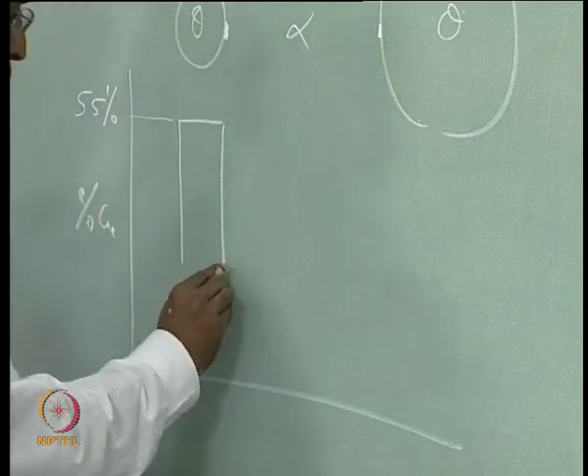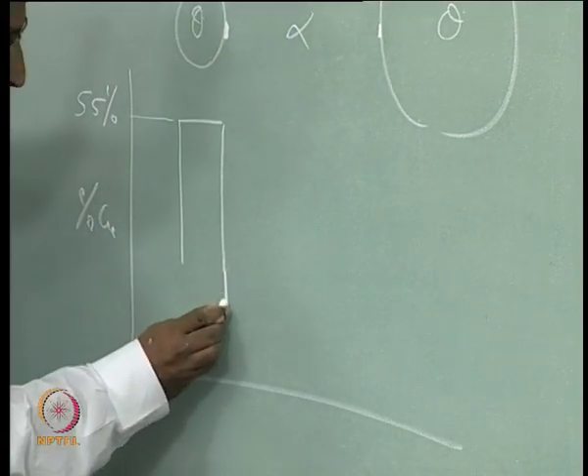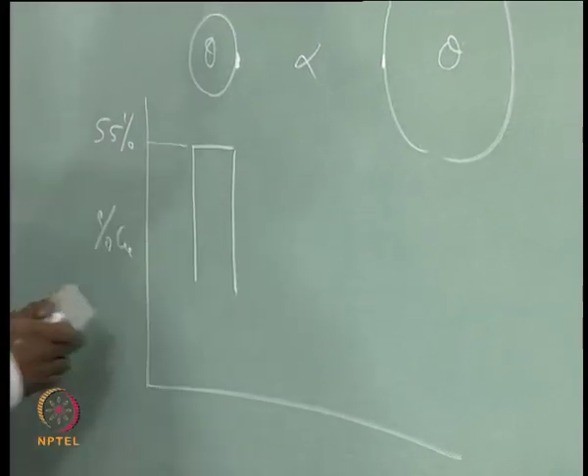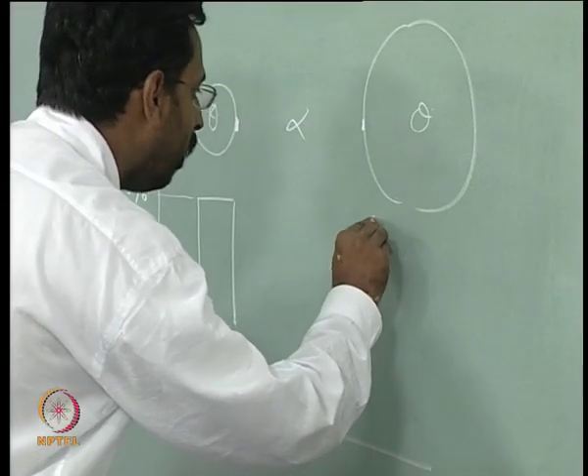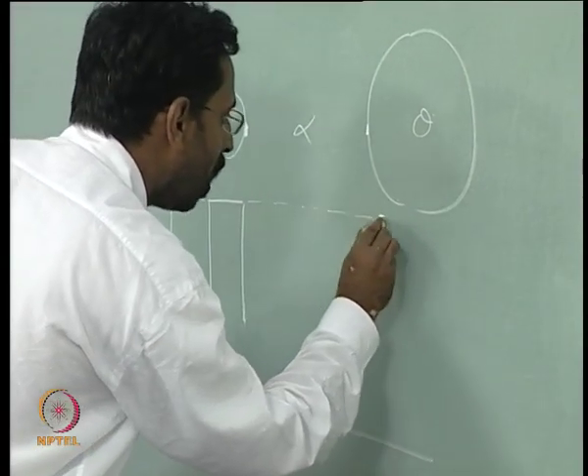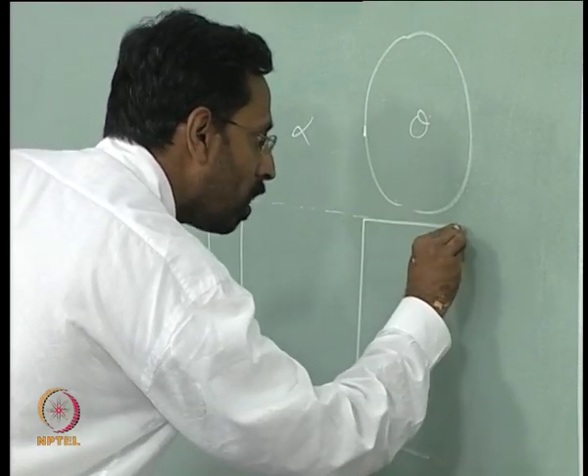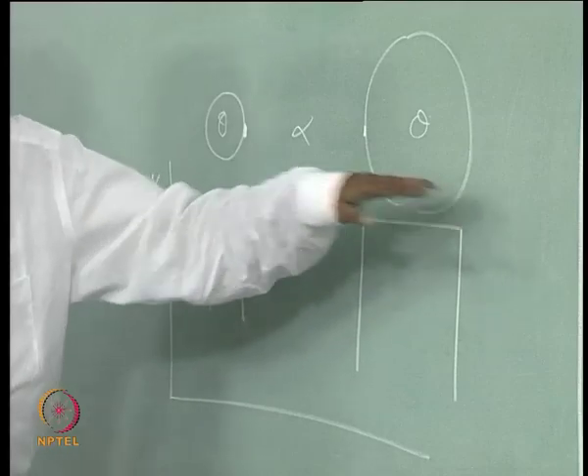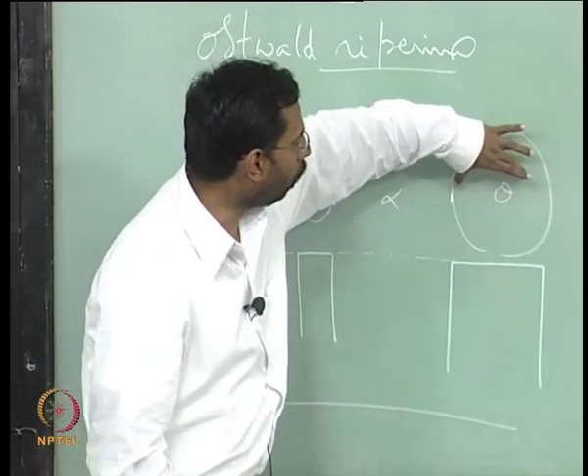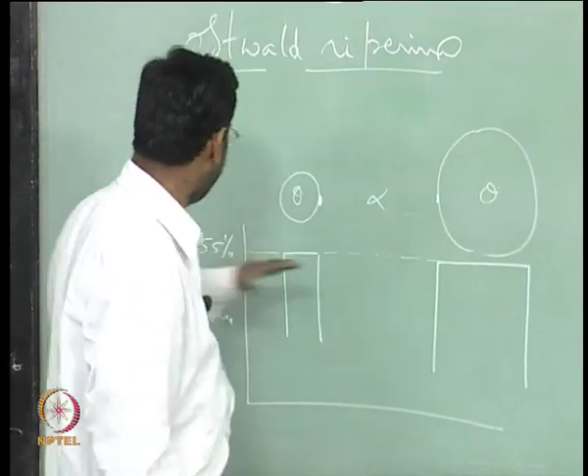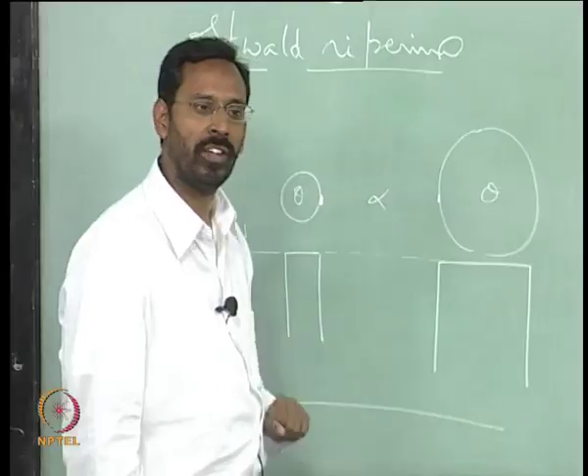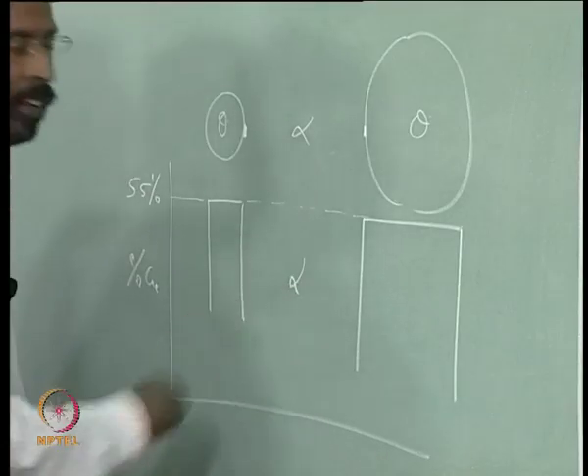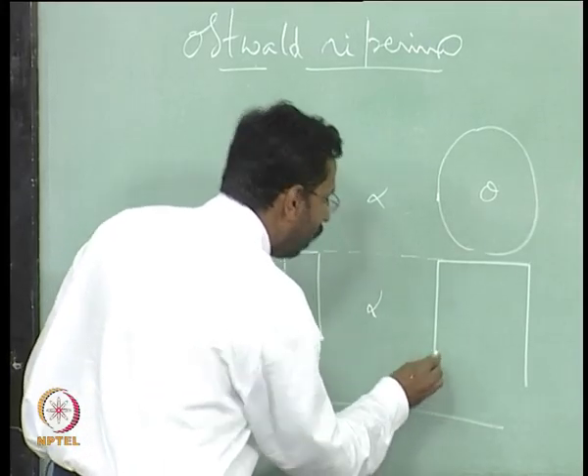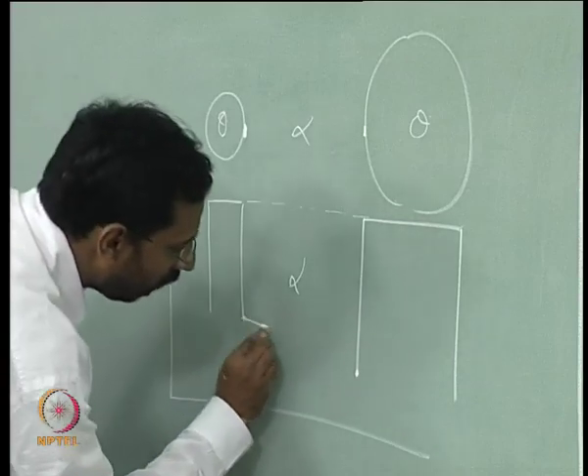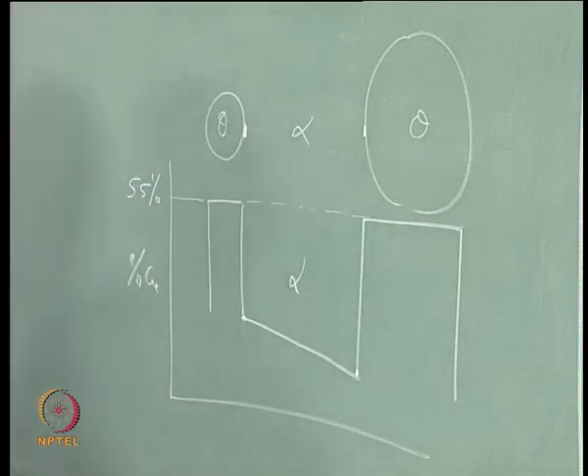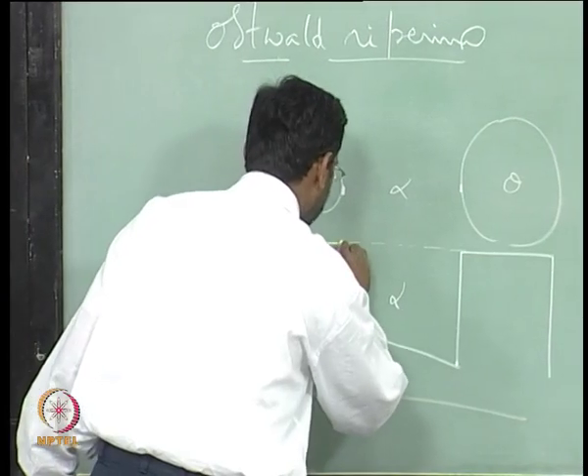Now, this is the composition of alpha somewhere here, which, just for the sake of understanding, let us again take this. The composition inside the precipitate is the same, it is the same theta, this whole thing is theta. So, the composition of the theta is this value. Inside the theta the composition is this, and then this is the alpha composition here, and the alpha composition here will be different. So, there is a gradient here inside this. If I look at the concentration profile, it looks like this.